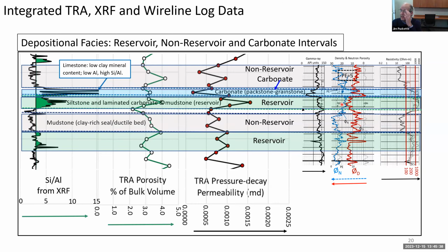This is just a close-up of one of the reservoir intervals. And we have reservoir here with, these are in millidarcies, 0.0015 millidarcy rock. That's our best rock. And porosity here reaches 4%. And I might want to point this out again. If we look at our uncorrected density porosity over here at 13%, and our tight rock analysis porosity at 4%, it just shows you the importance of those density porosity corrections for the matrix density, for the type of drilling fluid, and again, this was a water-based mud, and also for the organic matter content. And of course, if we looked at the previous slide, we saw that organic matter increasing. The more that organic matter increases, the more that correction is going to be.